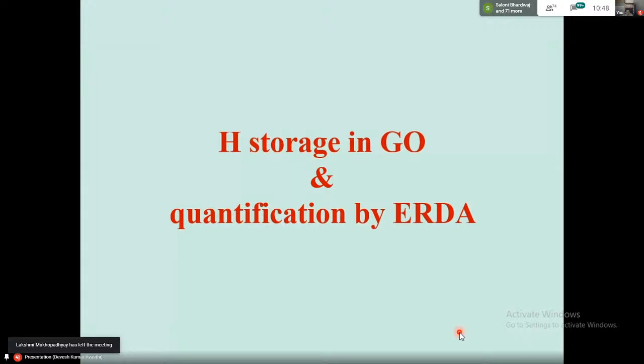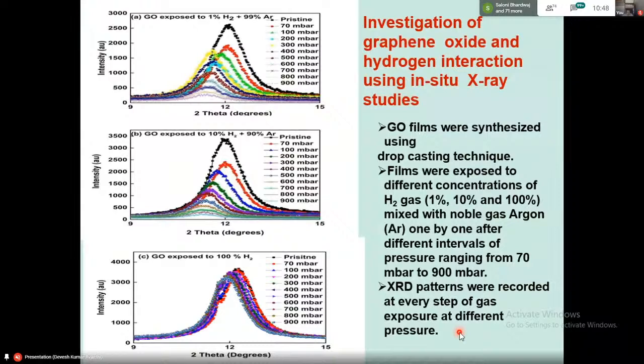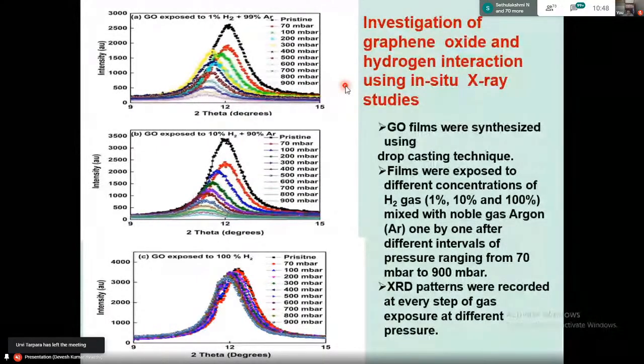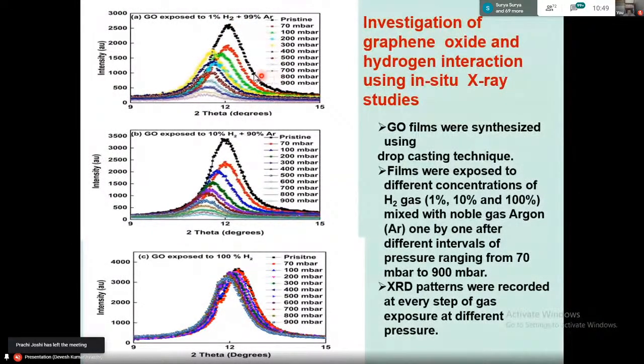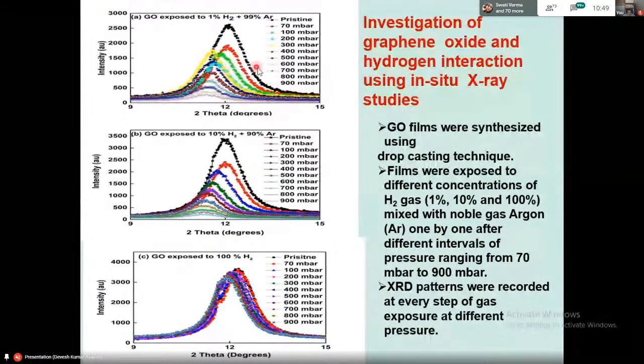So this is what we actually tried doing. We utilized GO, graphene oxide, and this was exposed to 1% hydrogen and 99% argon. And then we were trying to see, as a basic study, how hydrogen interacts with the graphene oxide. So this is the graphene oxide peak in the beginning, but once we put them together and increase the pressure of the gas, then this peak shifts. This shift in the peak is showing that the interspacing of the GO layers is basically increasing.